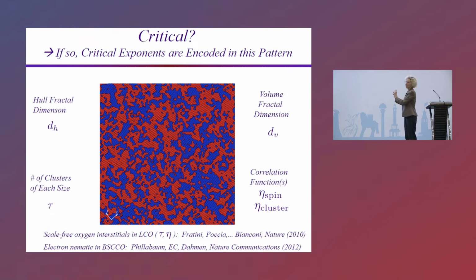So if this pattern formation is due to proximity to a critical point, then I claim that critical exponents are encoded in this pattern. We just have to learn how to get them out. We're used to deriving critical exponents out of experiment by a sweep of some parameter. So for example, we might measure magnetization versus a sweep of temperature and get one critical exponent, or versus a sweep in external magnetic field and get another exponent. Here, you don't have to sweep anything. In a sense, the sweep has already been done as a sweep in position. So there's enough information in here, I claim, to get critical exponents out.